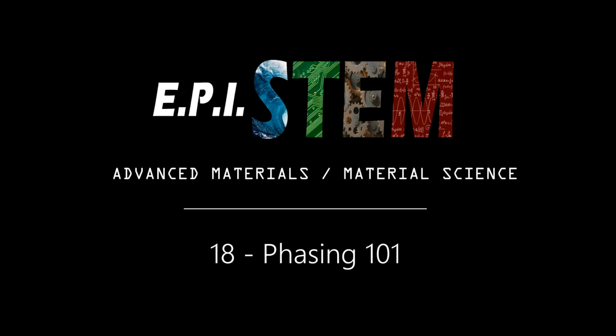the background. So what they do to achieve this is they have something that's already been developed, a Kevlar nanofiber aerogel film, KNA film, as it's referred to. One of these things is fabricated. It's a very thin, flexible, and highly porous material that acts as a good thermal insulator. So because it's porous, that means you can fill it with PCMs. So they put PCMs into this film and cover it with a hydrophobic coating.